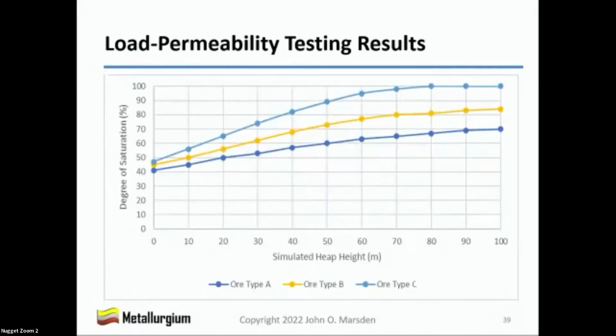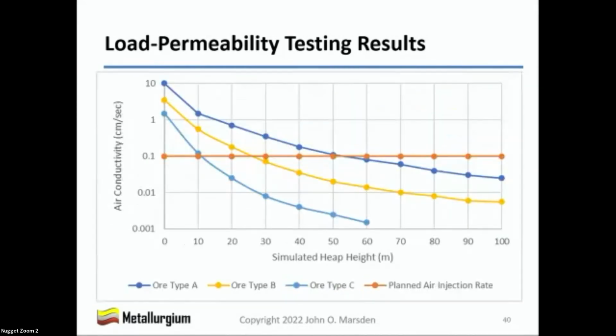Next slide. And as you would expect, the degree of saturation exceeded 85% at about 45 meters. So that's a massive flag for ore type C. And then the third slide shows that the air conductivity was impaired at about 10 meters for ore type C and 27 meters for ore type B. So air permeability is a big problem. When you're leaching chalcocite, air injection and air flow is critical. Next slide.